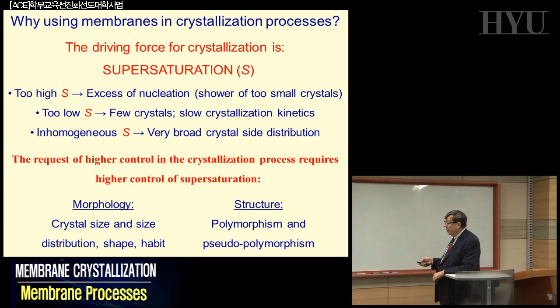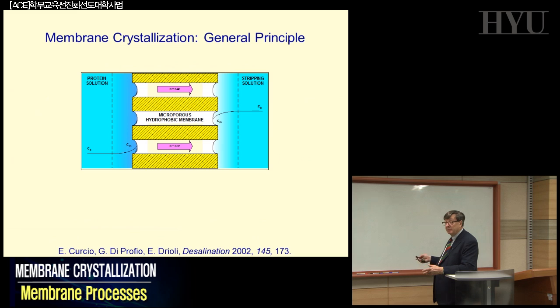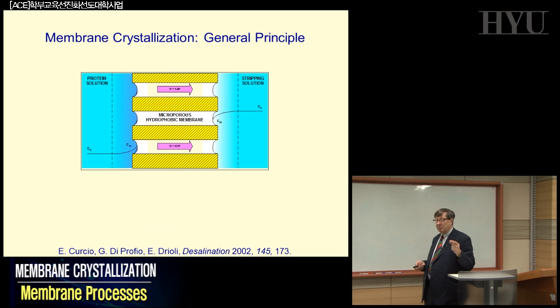And if you are able to do this, you can have control on the morphology, that means on the crystal size and size distribution of the crystals, on the shape, on the habit of the final crystal, and also on the structure. You can have better control of the polymorph, pseudo-polymorph, etc. Membranes can do the job. Initially, the idea to use membranes was just related to introducing a different way to evaporate the solvent. Working on membrane distillation, we learned that, if you remember, the transmembrane flux across your membranes is basically independent from the feed concentration, very different from reverse osmosis.